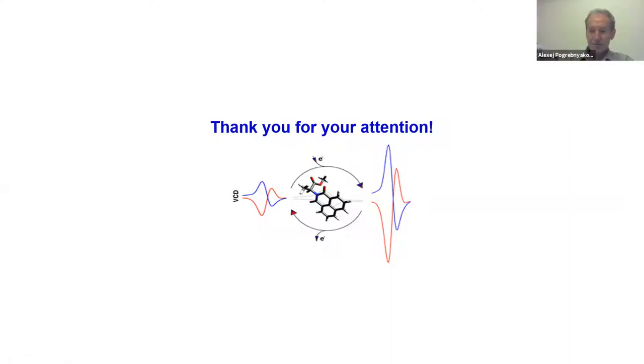I have a couple of questions. How did you deposit graphene on ITO or on other substrates? We use spin coating as well as drop casting and dip casting. Both drop casting and dip casting worked really well for us. You got single layer graphene? We had monolayer graphene, yes. In one case we had the graphene, which we have called GR, and in another case we had a reduced graphene oxide dispersion.